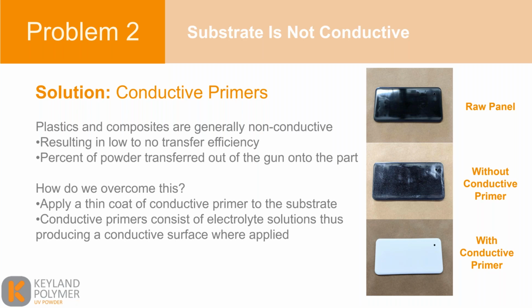The images that you see on your right here are plastic material. The top image is just the raw panel. The second image is an attempt to coat that material without the use of a conductive primer. And as you can see, there's little to no transfer efficiency of our powder coatings onto that part.